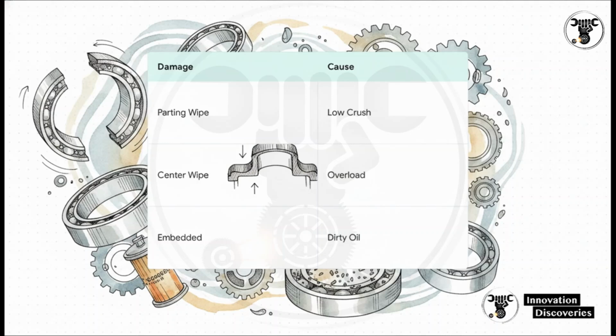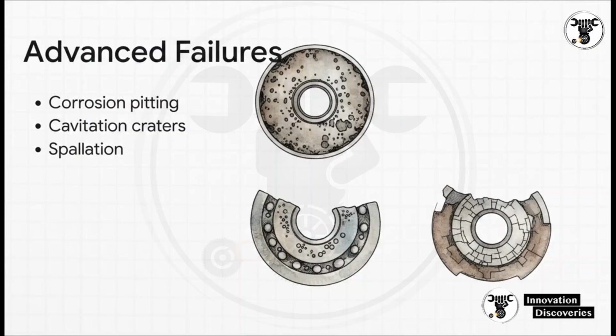But what if you pull a shell and see uniform even wear, but with tiny particles embedded all over the entire surface? That is a textbook symptom of extended oil change intervals or severely degraded filtration. That right there isn't a mechanical failure. That's a maintenance failure. Let's dig even deeper into the forensic evidence. If you see corrosion pitting, which looks like this rough, matte, porous texture right near the oil feed holes, your bearing was under chemical attack. This is usually caused by coolant leaks or highly acidic oil from, you guessed it, skipping oil changes.